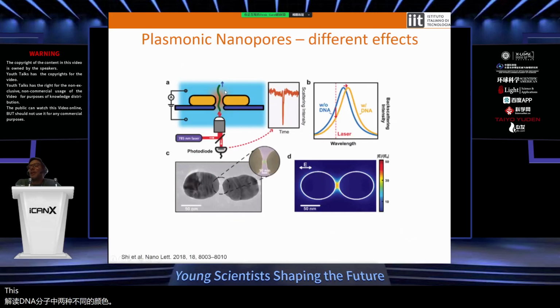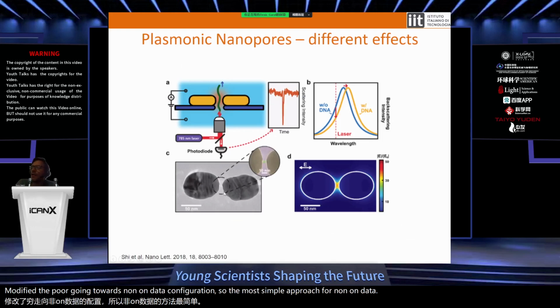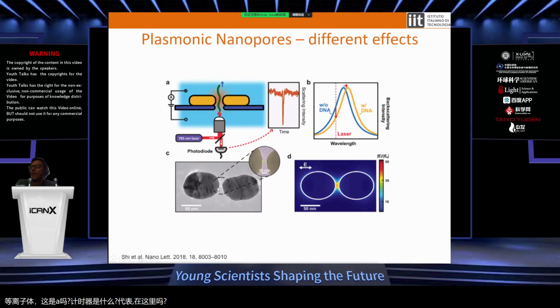This is not an optimized structure. What you want is to improve the properties of the nanopore, and the best strategy is probably to modify the pore going towards a nano antenna configuration. The most simple approach for a plasmonic nano antenna is a dimer, as represented here, and you can fabricate this dimer in order to have the nanopore in the gap.